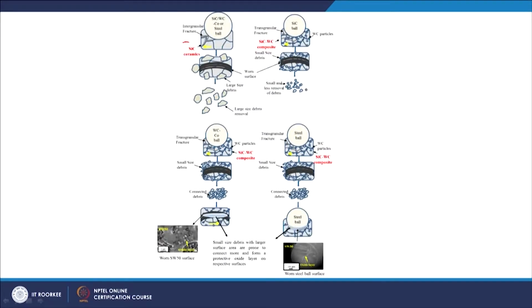So, summarizing the silicon carbide ceramics when you do not have any tungsten carbide, they just fracture by intergranular fracture, intergranular mode. So, this is actually the same against silicon carbide or tungsten carbide cobalt or steel ball. So, the larger grains came out as a debris, and when the silicon carbide contains some tungsten carbide particles, the composite shows a decrease in the size of the grain. So, the debris also will be smaller in size. So, the fracture we observed also changed dominantly from the intergranular to transgranular when you have the tungsten carbide particles in a silicon carbide ceramics.